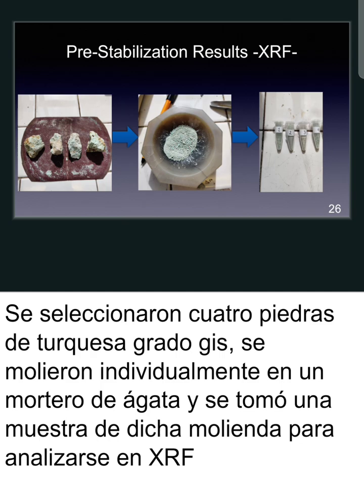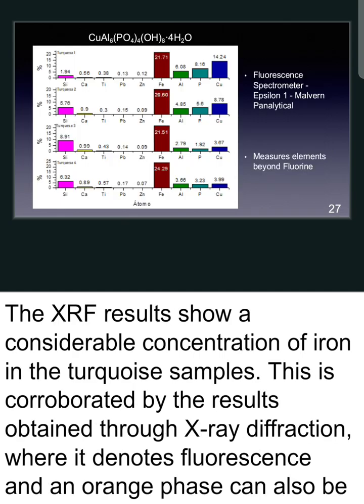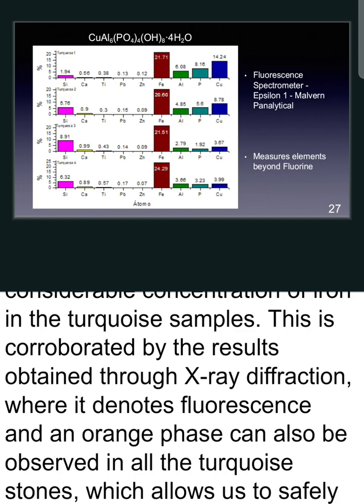The method was very similar to the X-ray diffraction. We ground the chalk-grade gems, and we took a sample of each one, and we went to analyze them in X-ray fluorescence equipment. These are the results. The X-ray fluorescence results show a considerable concentration of iron in the turquoise samples. This is corroborated also by the results obtained through X-ray diffraction, where it denotes a fluorescence and an orange phase